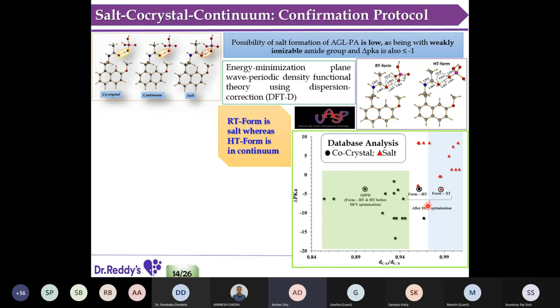So what happened? The RT form became a salt, and it's sitting nicely with the cluster of other salts. There is no ambiguity. At the same time, the HT form became in between, and that's what we used to call a continuum. In summary, the RT form is a salt, whereas the HT form is in the continuum.